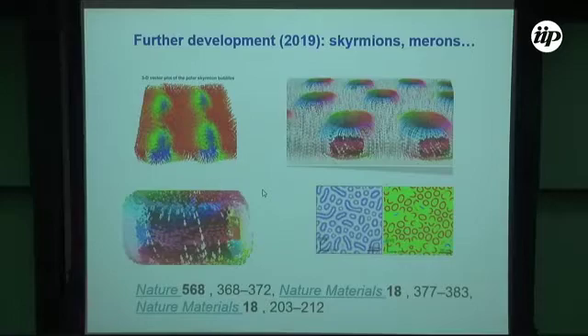And then an explosion in 2019: people drew a lot of pictures that are supported by experiment. Now in 2019 it becomes the subject of at least three Nature publications. They observe really more sophisticated structures of these vortices. Sometimes they form not really a stripe structure, but a point-like structure, but this is well known in magnetism as bubble domains. No, it's purely electric, no magnetic field at all. But the electric field plays the role of the magnetic field in ferromagnets. And what I'm claiming is that the role of the electric field is much stronger than in magnetic systems. So here this effect becomes much more visible.